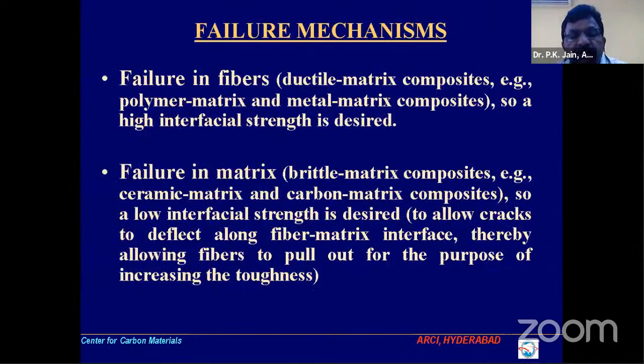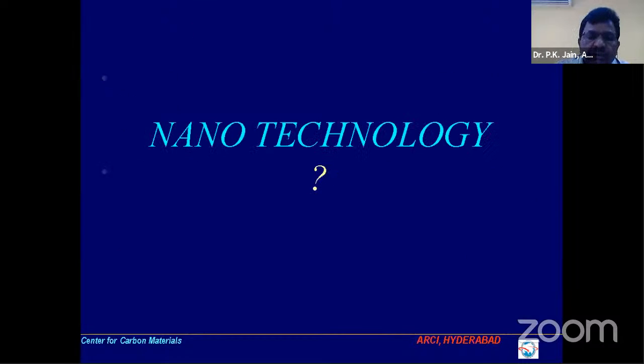So the failure mechanism can be explained in two simple lines. The failure in fibers: if it is a ductile matrix like polymer matrix or metal matrix, a high interface strength is desired. That is one conclusion. And the second conclusion, if it is a brittle matrix like ceramic or a carbon matrix, a low interfacial strength is desired to allow the cracks to deflect along the fiber matrix interface, thereby allowing the fiber to pull out for the purpose of increasing the toughness. This is very important, and this work I have presented in the US also long back. And this was published in Carbon Journal.